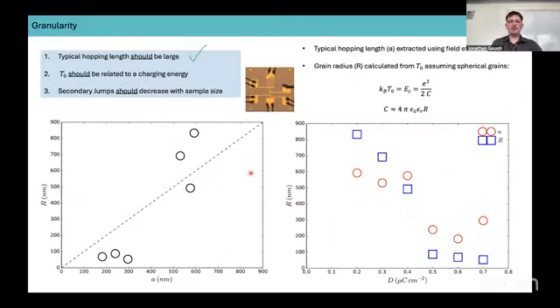So we can make three predictions of this model. The first is that the typical hopping length should be large because it's given by this average grain separation, which we know to be true already, typically 600 to 700 nanometers. T0 should be related to a charging energy rather than an average energy distribution due to the disorder. So we can make a very simple approximation of this by assuming T0 is given by e squared upon 2C, so a charging energy, and we assume a capacitance associated with spherical grains, and then we compare that with the measured value from the linear voltage term. The linear voltage term is given by these red circles, and the grain size is given by these blue squares. So we see this nice correlation between the two, which is encouraging and in support of this granularity model.